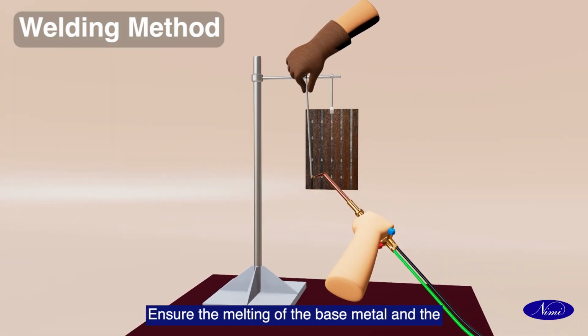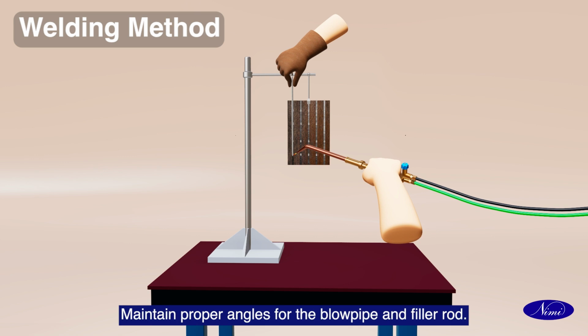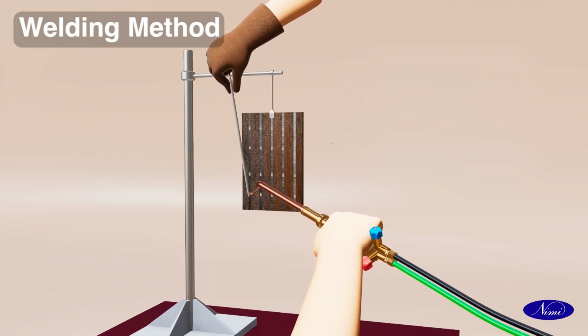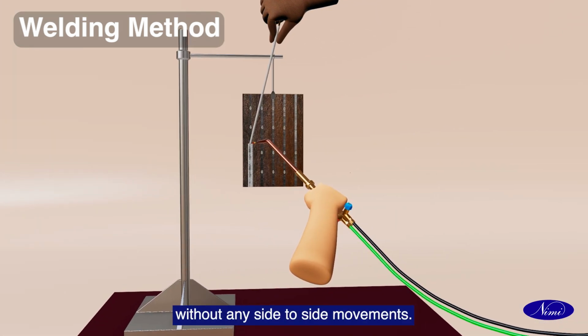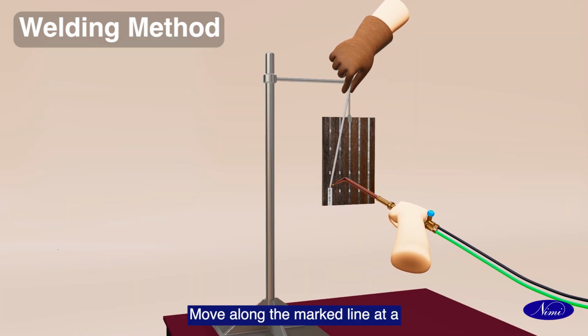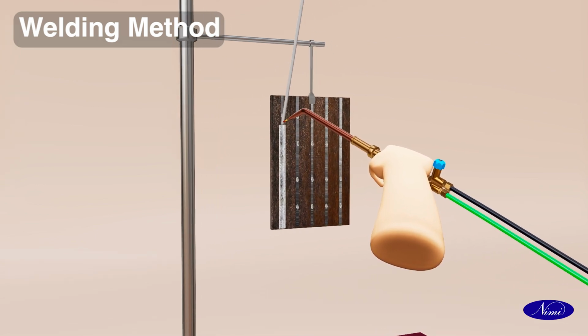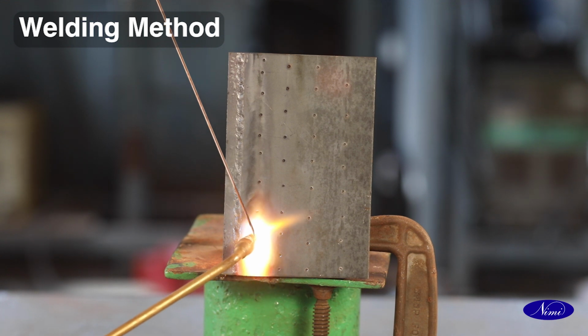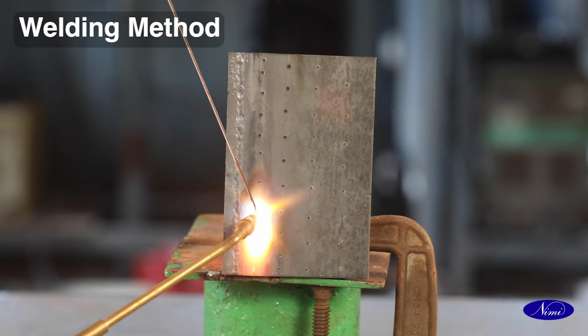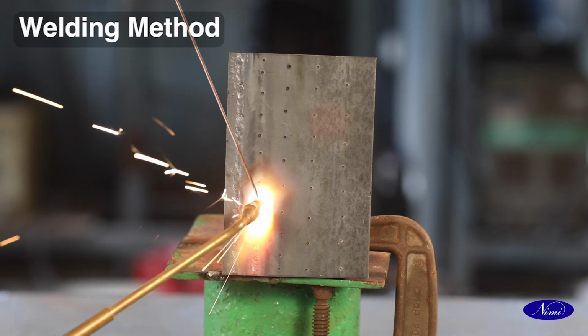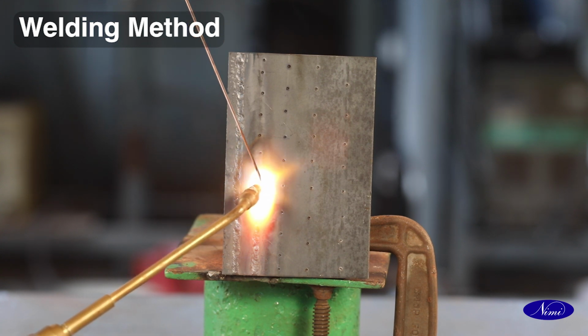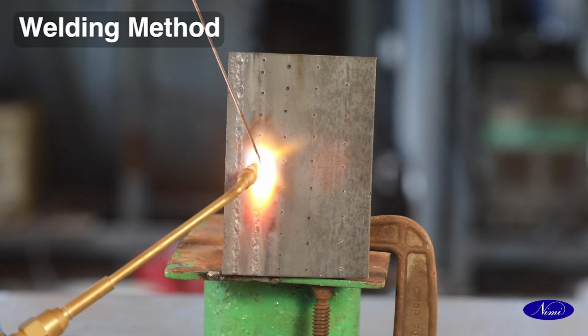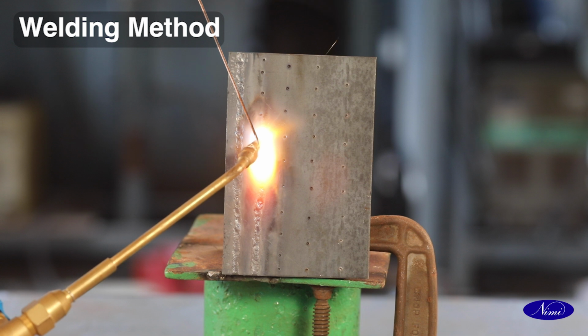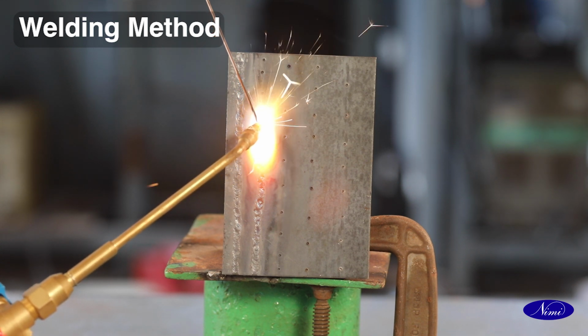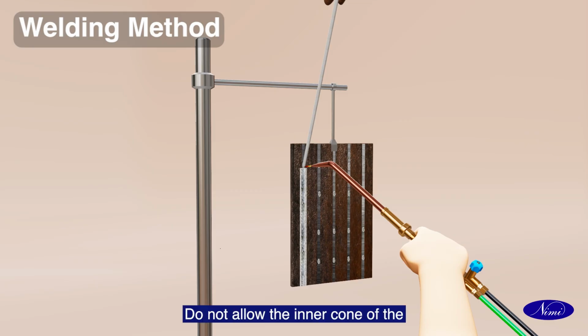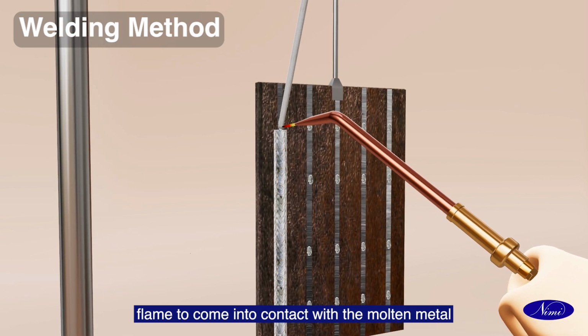Ensure the melting of the base metal and the filler rod is kept to a minimum as possible. Maintain proper angles for the blowpipe and filler rod. Move the blowpipe and filler rod without any side-to-side movements. Move along the marked line at a uniform speed in an upward direction. Do not allow the inner cone of the flame to come into contact with the molten metal to avoid a backfire.